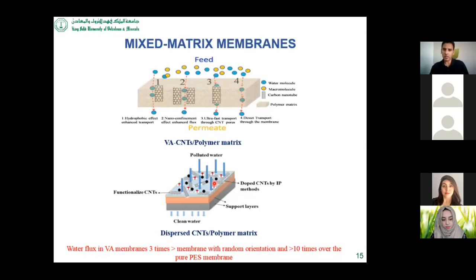Here, the structure is the same, but the carbon nanotubes are randomly dispersed. In this case, we can expect comparatively less flow of water, because some of the channels, for example the flow through the interior of the CNT, will not be available here. So the flux in this type of membrane, where the CNTs are vertically aligned, is high compared to this orientation where the CNTs are randomly distributed.